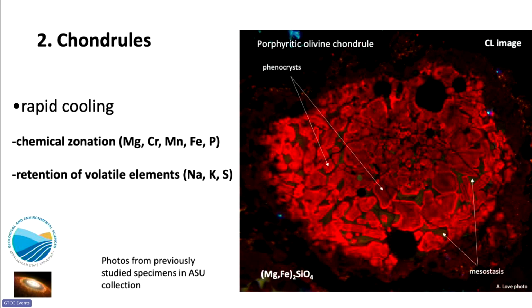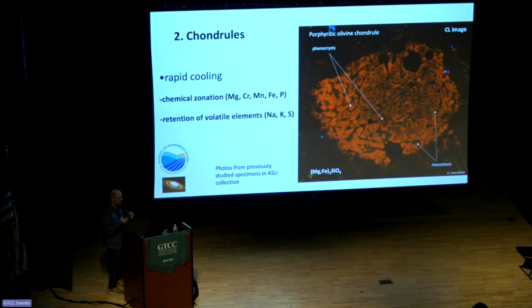We also have this dark yellow area that we call mesostasis. And mesostasis is really the name of a material that's left over, that's composed of all the elements after we used up all the magnesium, iron, and silicon to make the olivine. In addition to elements like aluminum, silicon, calcium, we get volatile elements like sodium, potassium, and sulfur. And so when we see these two features within a sample that grew from a melt, we knew that that melt had to crystallize very rapidly, because if you hold these at higher heat, those zoning features disappear and we evaporate off all these volatile elements.